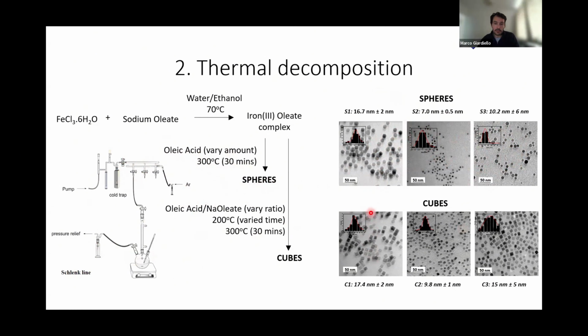And on the one at the bottom as well, we have exactly the same principle, but with cubes. So these are spheres, these are cubes, large cubes, small cubes, and poorly dispersed cubes. In principle, what we wanted to see was, we're investigating anisotropy. These would be too small, probably, to fully saturate. They wouldn't be strong enough to fully saturate in the system. So they would be a poor signal, and these would be a large signal.